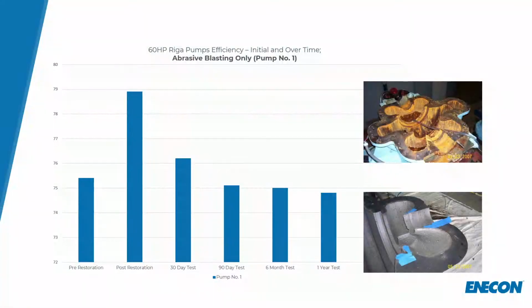We can see in this case here, this one pre-restoration, so they didn't do anything to this. You're running at just a little bit over 75% efficiency. Now post-restoration, look, you're coming up to 79. Not that great, but you are a lot higher than you are here. But now after 30 days, after 90 days, after 6 months, and after 1 year, you're kind of getting this again because there's no protective coating applied, and you're kind of right back where you started. So in other words, it really didn't give you a lot of good evidence, a lot of good data.